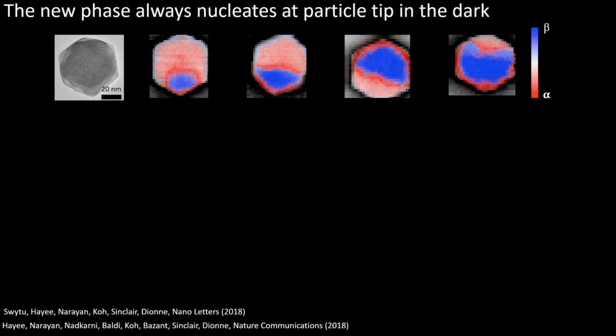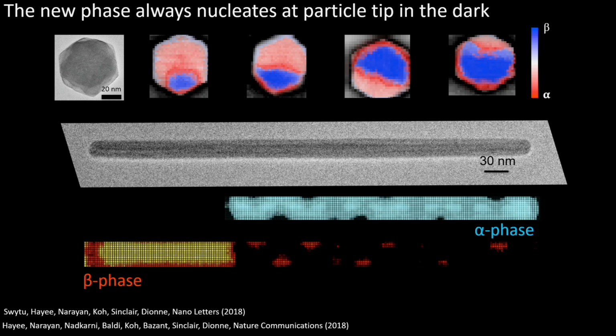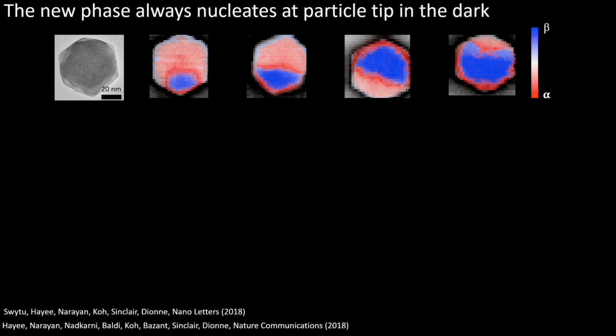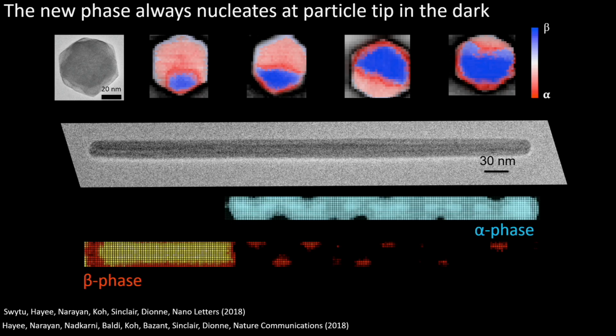And what we found in the past decade is that regardless of your nanoparticle shape or size or crystallinity, basically the hydrogen is always going to split and intercalate at those low coordination number sites. So that was a cube that I showed you with 100 terminated facets or faces. Here is an octahedra with 111 terminated facets. And again, you can see the new phase intercalating basically from the octahedral corners. Similarly, for these nanorods, we also have hydrogen basically splitting at the tips and then going into the rod. So when we are in equilibrium, we don't have any lights on, but we're just controlling things like the temperature and the pressure.